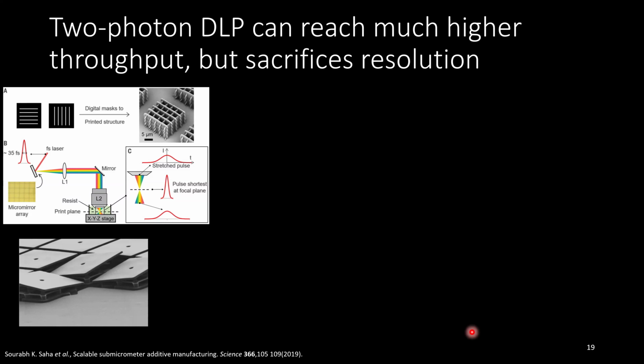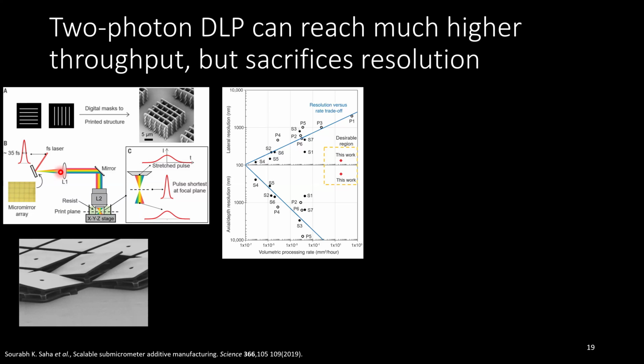And so this was demonstrated in this paper from 2019 that is not in any way related to us, where essentially they take their femtosecond pulse laser, which you need to get this two photon effect. They project it onto a digital micro mirror array, DMD, which has these mirrors that can basically be flipped on or off. And then that acts as sort of a digital mask that you then image into your resist material, project that mask, and you can create structures. And they were able to print polymer in air.